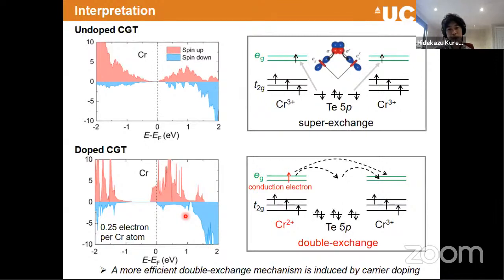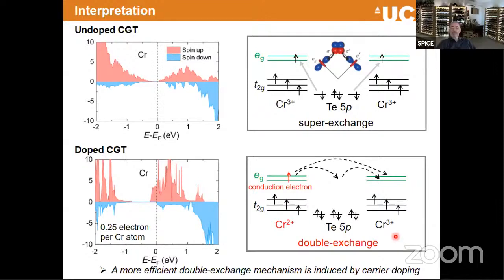And then by just simple calculation, we found that it's pretty much 1 in 4 electrons for chromium that has been doped. Although, because this is delocalized, we couldn't differentiate between these very easily. But we just say that 25% of chromium 3+ is doped. Does that make sense? Yeah, go ahead and continue.